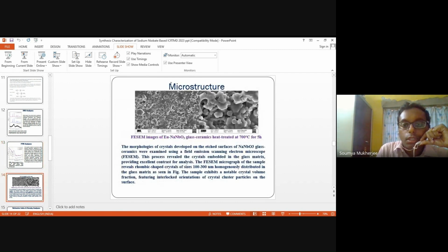The microstructure is shown for the lowest temperature heat treatment system, carried out for 5 hours, and the microstructure is a quite packed system, and the crystallite size, the particle size, are quite big, that is 100 to 300 nanometer, homogeneously distributed. It is a densely packed structure with rhombic shaped crystallites, with minimum porosity and interlocked features that have been observed. And one of the most important things is that to observe the contrasting features within this glass matrix, we have to etch the sample with HF solution.